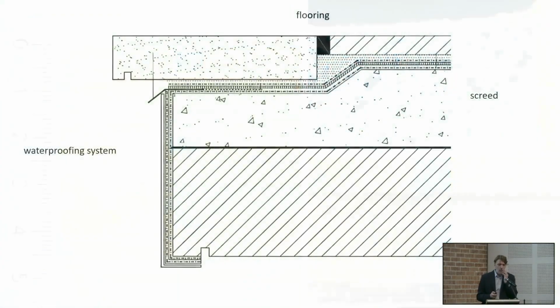So, what normally is done in the stratigraphy to stop the water? Normally the waterproofing system is based on the structure. This is concrete, and then we have the stratigraphy of the floor, the cement leveling, and then the tiling. This is the traditional way. You see the waterproofing system is placed right on the structure. So it means that the concrete is protected, but when it's raining and the water is getting into the joint, it will pass through the screed to the cement layer and will be stopped at the level of the waterproofing. So the cement over there will be wet, correct? Because the water can pass through. And when the temperature grows, the water will go out, evaporate, and we go back to the problem we saw before. So we may have efflorescences on the surface of the tile.